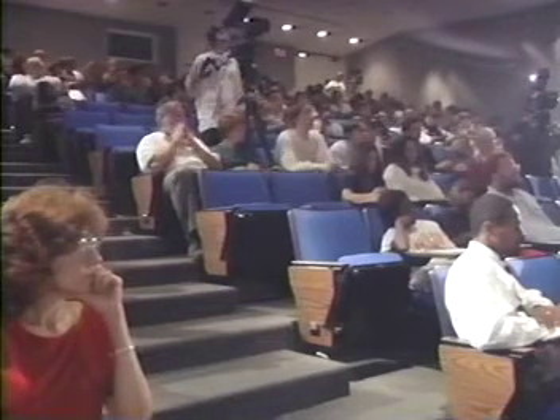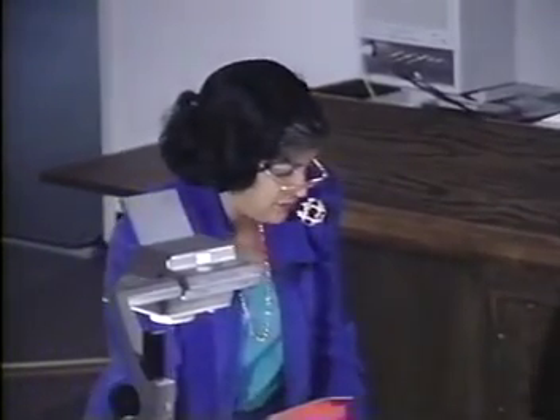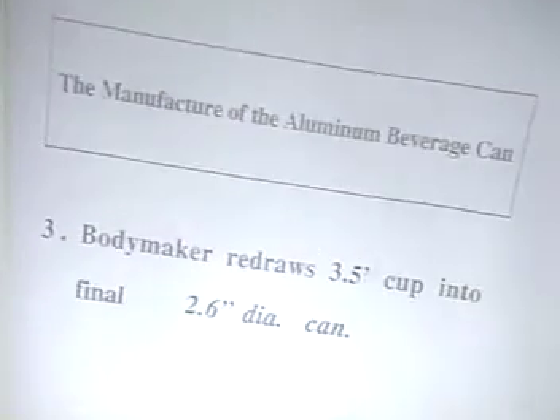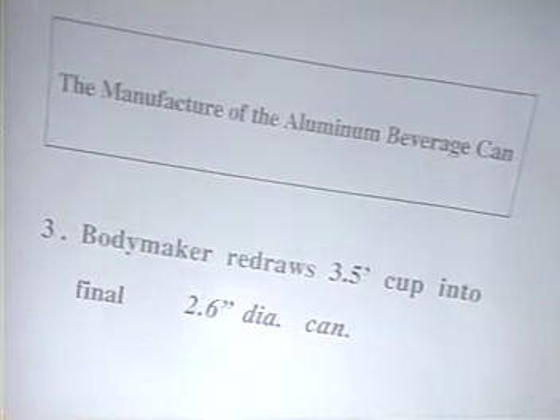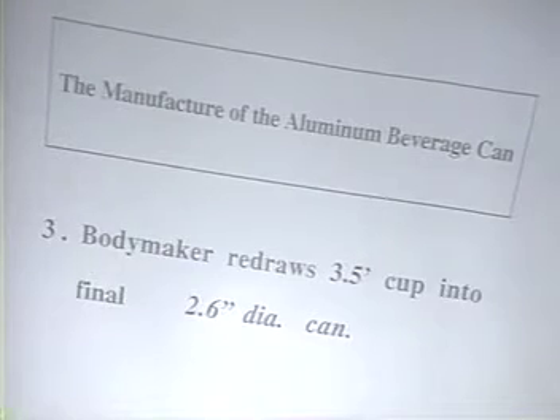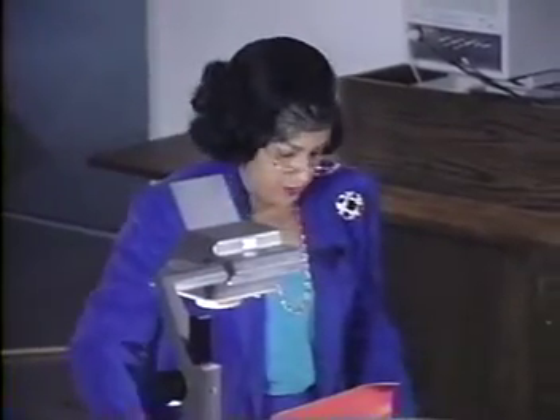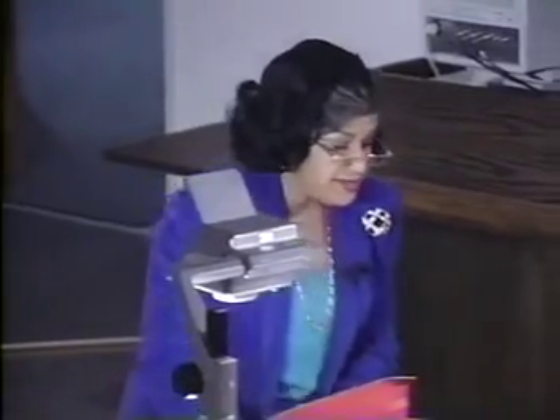Also, we have to be concerned with the ratio of the blank diameter to the punch diameter. We have to be concerned with the corner radii, so they're not so sharp that they actually puncture the material. And obviously, because we're pushing like a plunger, if you will, on top of this plate, we've got some friction and lubrication problems. So these are some of the things that we have to think about in this process. Okay, so now we've got the final 2.6-inch diameter can. And the next thing we do is iron this can.